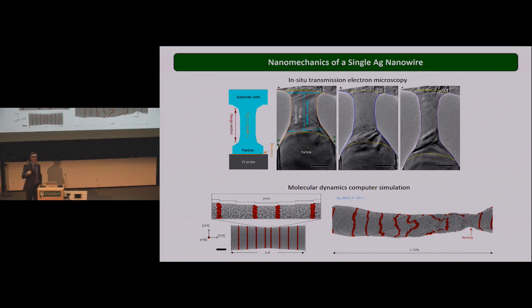Of course, mechanically, it's very hard to test this crystal. This is just an example of how it's done here. You need to attach a particle to a probe, which approaches and sticks by cold welding to a substrate on the other side. You really need to have a talented researcher and graduate student to do this, so it's really tedious work. And on our side, we do molecular dynamics simulation. I would have to say it's a little bit easier for us because we can design the wire with steps and so on, and we can measure the ductility of the material.